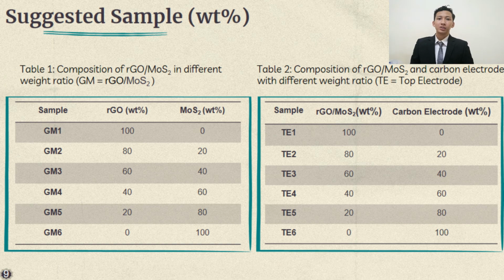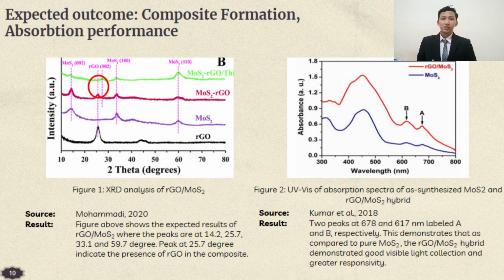Suggested samples for our experiment are shown in Table 1 and Table 2. At the end of this research, the expected outcome is, first, the synthesis of RGO-MoS2 was successfully executed via the solution processable method, confirmed by obtaining the same XRD result as shown in Figure 1. Next, the UV-Vis spectra analysis is expected to obtain the same result as Figure 2, which says that the presence of RGO-MoS2 provides good absorbance performance and greater responsivity.